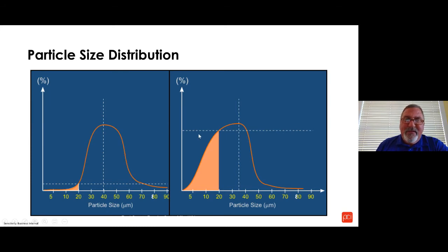Now, as you reclaim, you start to, and let me back up, this is a cartridge type system example. If you have a cyclone type system, it actually scalps off all the fine particles and you don't see this. But if you have poor fluidization in your reclaim hopper, and it transfers over to your main gun feed hopper, then this may be a reason why this is occurring. As you build up fines in the system, they do not like to fluidize. They do not charge well. They don't accept the electrostatic charge very well, so they're basically just taking up space. When you get to this point, we would typically recommend that you run the hopper down as low as possible, discard that powder, and start the process again with virgin powder.